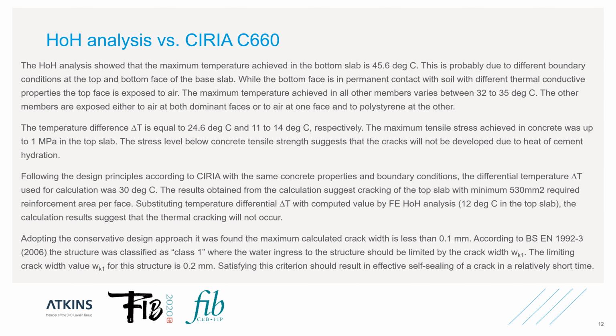The FE HOH analysis showed that the maximum temperature achieved in the bottom slab is 45.6 degrees Celsius. This is probably due to different boundary conditions at the top and bottom face of the base slab, while the bottom face is in permanent contact with soil with different thermal conductive properties. The top face is exposed to air. The maximum temperature achieved in all other members varies between 32 to 35 degrees.